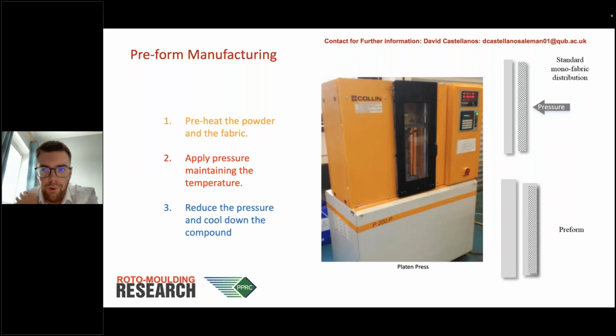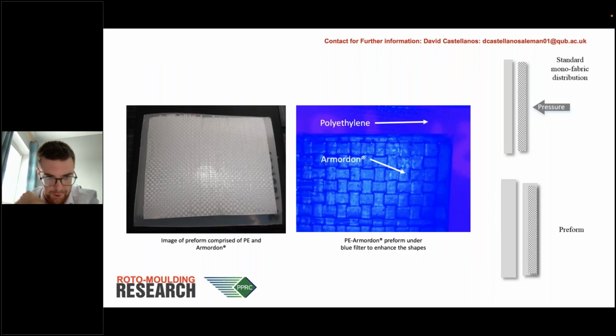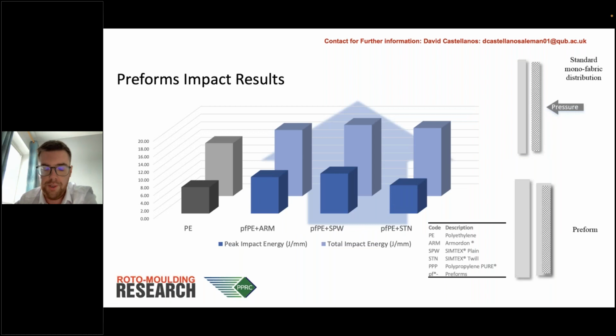And one of the conclusions that he came to after doing all of that process was that it's actually easier to produce preforms by compression molding the composite into a polyethylene bed, first of all. And this is an example of what that looks like. So you've got the polyethylene matrix itself, which is well compressed within the composite material itself. And he then went through a series of iterations to try and perfect which material gave the better mechanical properties. And in most cases, he was finding that by placing that material into a rotationally molded part as a preform, he was getting consistent mechanical performance improvements.